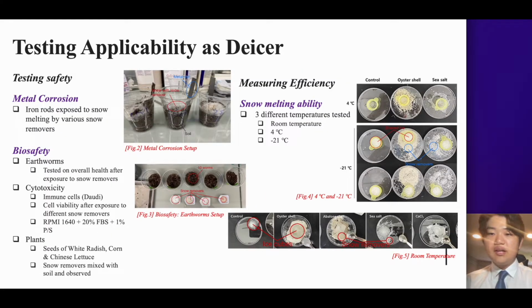To examine the applicability of oyster shells as a de-icer, the ice melting rate and metal corrosion characteristics were analyzed and the biosafety of oyster shells was tested. First, the metal corrosion characteristics were tested by exposing a metal rod to an environment close to the real-life setting. The metal rod was inserted into soil, snow was sprayed and left to be melted using different de-icers, and then the metal corrosion characteristics of the de-icers were analyzed.